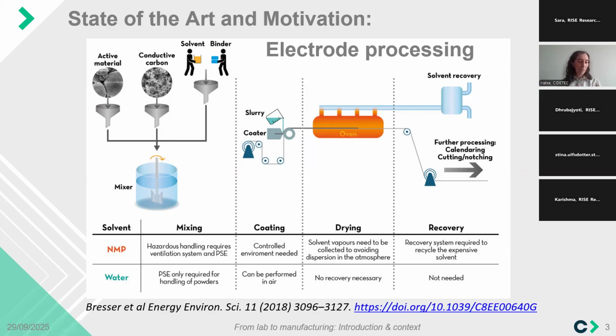is resolved, or is not an issue anymore, when using water as the solvent and dispersion medium of the electrode components. As we can see in the scheme, we have the active material, the main component, but also a series of conducting additives, mostly based on carbon, and the polymer, the binder that brings everything together and keeps the mechanical stability and adhesion to the metallic substrate - aluminum in the case of cathodes - the foil that gets bound when assembling the cells. In this scheme you see the advantages of using water as this dissolving, dispersing medium instead of NMP.